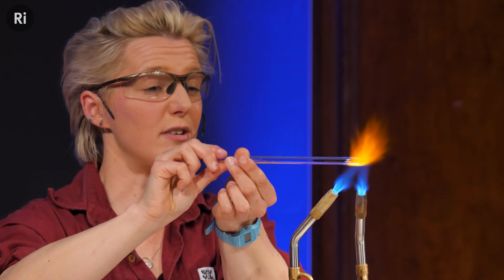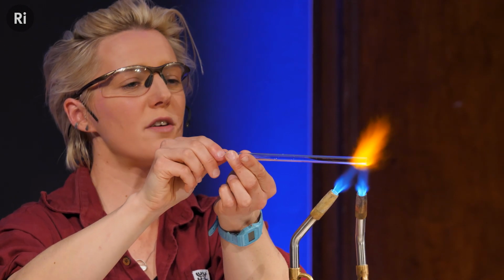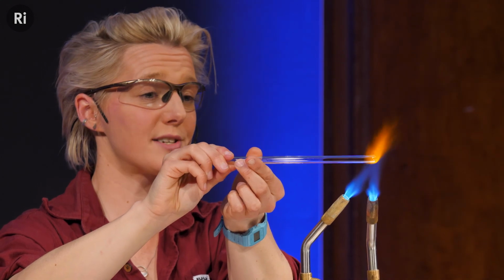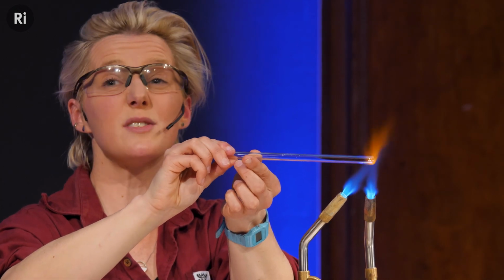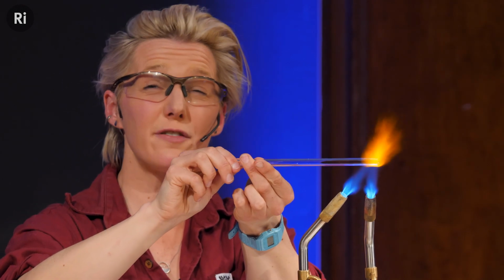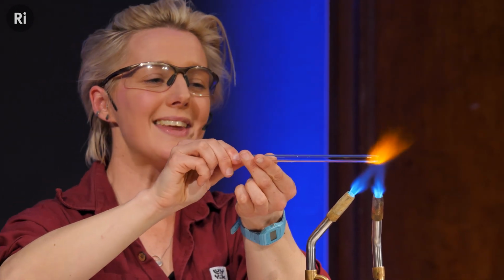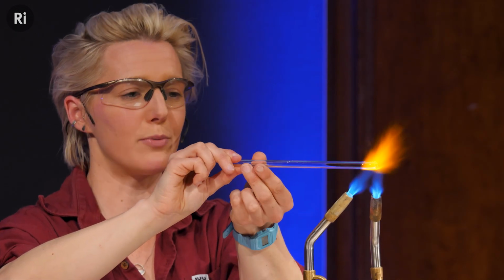And so in those sorts of materials, like ice, we all know ice, when you heat ice to 0 degrees, it melts, right? And that happens because all of the atomic bonds in ice are identical. So at exactly 0 degrees, that's enough energy to make those bonds break and to form water. But in glass, it's different. In glass, all of the bonds have kind of different strengths. There is no one particular structure to melt. And so what happens is as you heat it up over a few hundred degrees, the bonds gradually break. And so the material goes from being very hard initially, and then it gets softer and softer and softer until eventually it starts behaving like a liquid. But there is no one melting point.